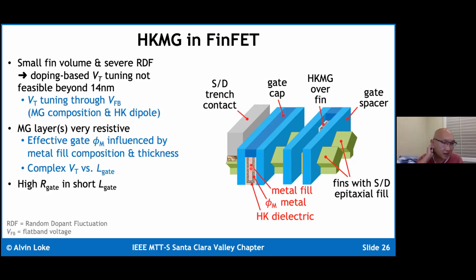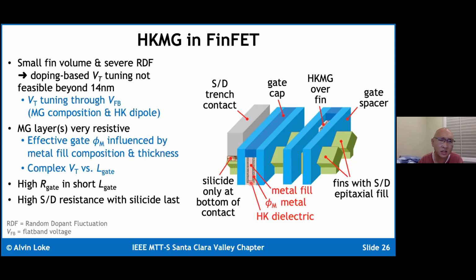One thing that hurts RF very dramatically, and also logic for that matter, is the fact that the gate resistance is also very bad in these scaled nodes. And so non-quasi-static effects are increasingly prevalent. And lastly, because we have gone to a silicide last process I mentioned earlier, the fact that we have these silicides only at the bottom of the contact, not strapping the entire diffusion, it basically means that the source drain access resistance to the transistor is very high.